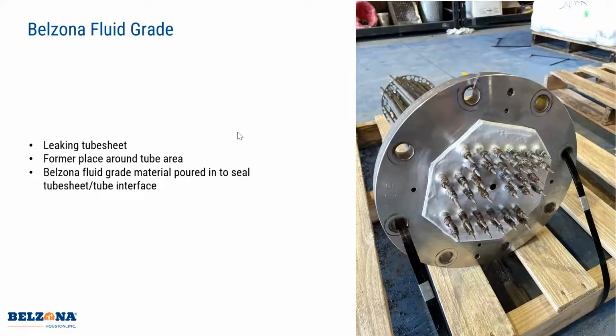So this was a tube sheet, not too big, just a little tube sheet, but it was leaking at the interface of the tubes in the tube sheet. Stainless steel, critical equipment, expensive. You know, even though it's small, it's a stainless steel tube bundle. Takes time to make them, to get a new one fabricated, and they really needed this one quick.